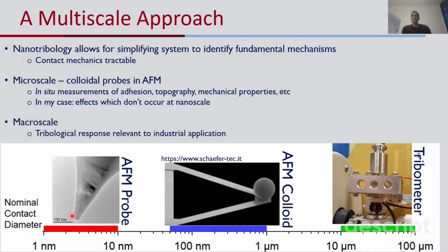And finally, we look at the macroscale. So we do experiments to measure the friction response when you have nominal contact diameters above 10 microns or so. And this is important because this is the tribological response that's relevant to industrial application. You can extract things like the friction coefficient and the wear coefficient that will be useful to anybody trying to apply these materials in the industrial world. But additionally, if you gain insights about what's happening at the smaller length scales to apply them at the larger length scales, you have to know empirically what the response actually is at the larger length scales.